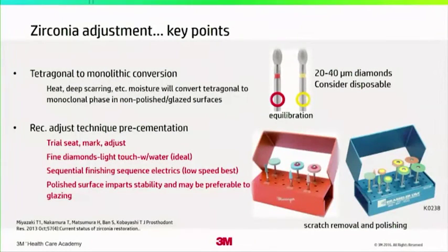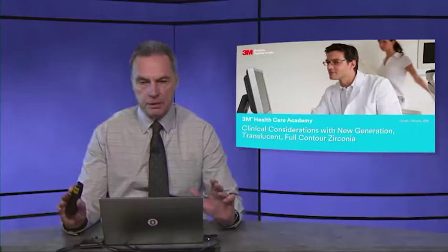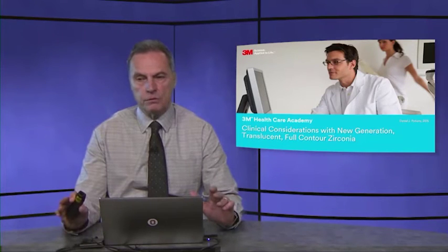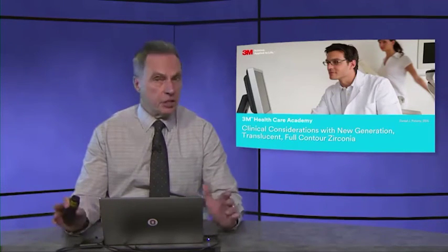Now, zirconia, whether you have not used it or have used it more commonly and have experience with it, you're going to notice that it's a very, very hard material. It doesn't lend itself well to a lot of adjustments, and particularly if you ever have to remove one of these, you'll understand what I mean. It's not the easiest material to remove. But in order to make this work better for us, we need to demonstrate a fair level of care when it comes to protecting the restoration itself. One of the most common reasons zirconia can fail is simply not adjusting the restoration properly.